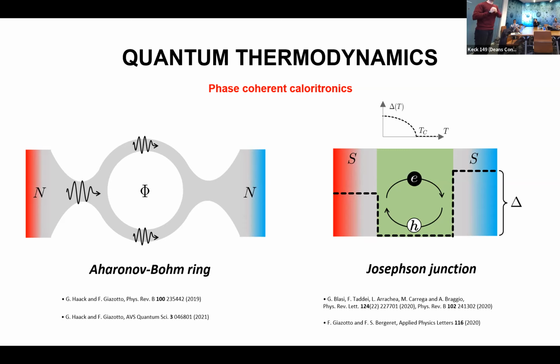And by doing this, you can create a kind of interferential mechanism inside the system. And by exploiting this interferential mechanism, one can generate thermoelectricity. Namely, you can produce fluxes of charge currents simply by applying a thermal gradient between the two leads of the ring.